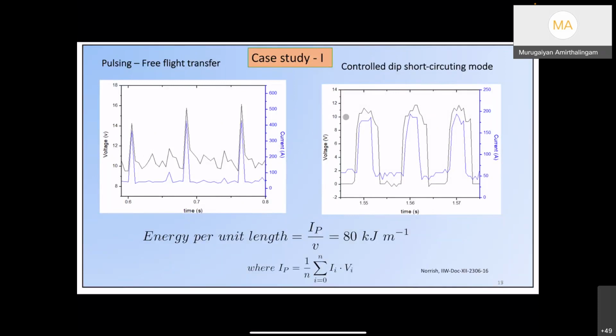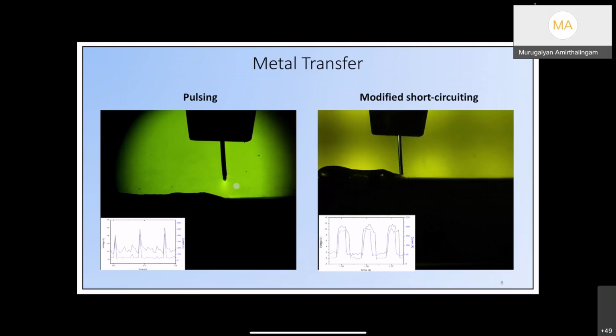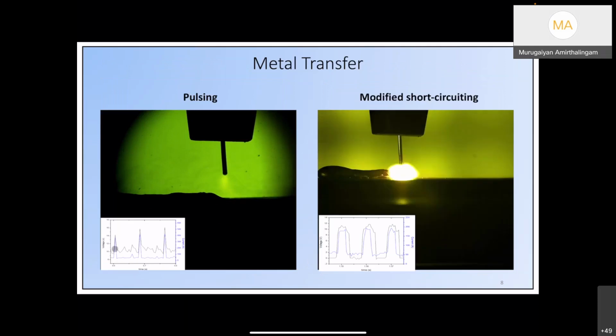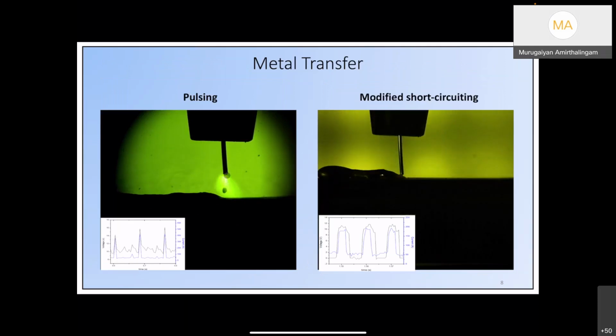We can have identical arc energy or heat input in these two cases. If you look at these two waveforms, the actual energy, the heat input, would be identical. But the microstructure we get will be completely different. Why? Because when we use a pulsing waveform, we give current pulses to create a high energy density arc during every current pulse, and that ensures that the tip of the consumable melts and gets deposited.